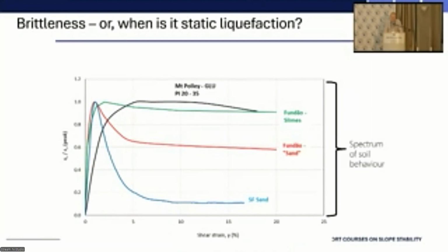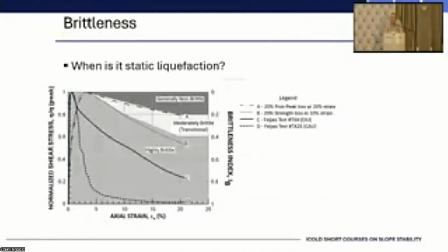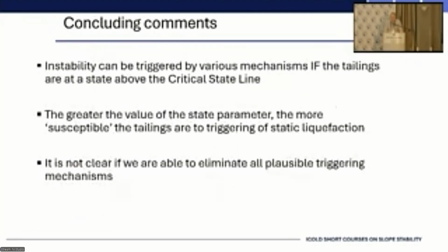If we start doing K-naught consolidated, we get even more brittle behavior, as shown by that curve 1 there, going back to the ICOLD. That curve 1 is from Feijão or Brumadinho. It was K-naught consolidated, and you'll see a really, really small strain required to mobilize peak, and then massive strength loss over a small value of strain. So, wrapping up, and I'm going to kindly give Alecha about 4 minutes extra.